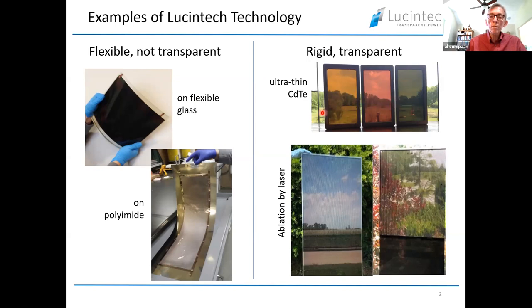with the idea that this could be put into windows. Our last work is in collaboration with a company called Toledo Solar. And in this case, we're actually taking a standard panel. This is now a 2 foot by 4 foot panel. And if you put it in a window and look from the inside, this is the visibility you see from the inside. This is done by a laser ablation process where we're partially removing some of the coating. And this is the same panel, but taken outdoors and looking in reflection. So you still get very nice reflection from the panel. So the idea is that this could be used on buildings. Anyway, I'm going to give a little overview of most of our effort with semi-transparent materials.